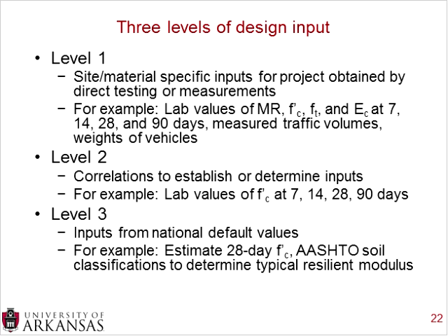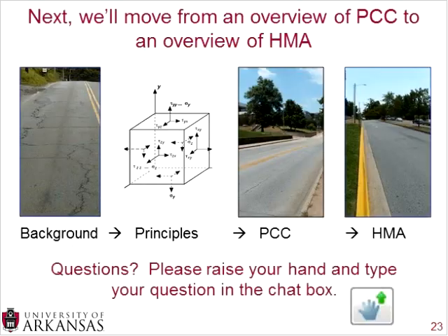And finally, the last level, level 3, is using inputs from national default values. An example of this is you can estimate the 28-day compressive strength of the concrete. So you simply enter in a default value of typical concrete. We know that there's ranges out there, and you can just put a default value in. Another example is using AASHTO soil classifications to determine resilient modulus. So instead of actually going out and taking samples from the field and directly measuring the resilient modulus, you just classify the soil and then that can give you a resilient modulus. So as you increase levels, you get less detailed, but it does decrease the amount of testing you need to do and the amount of work you need to do up front.